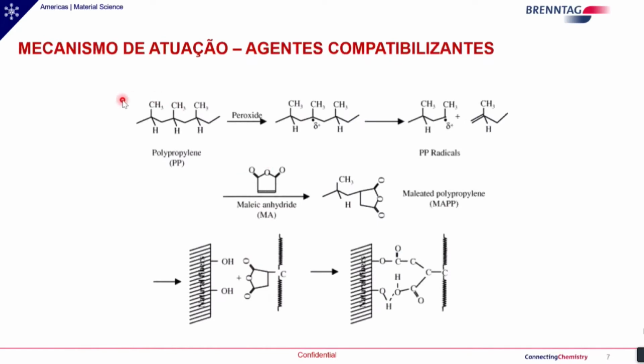In this slide, you see an example of production of a polypropylene with a graft, with maleic anhydride. So there is a graft performed here. We have the polymer matrix, which is the polypropylene. Here we see the structure of the polypropylene. We add peroxide to the formulation. The peroxide then breaks the polypropylene chain, and at this point here, there is a free radical which will bind to the maleic anhydride molecule.